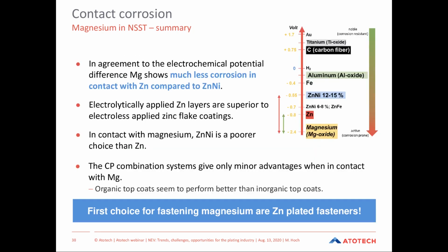To summarize the magnesium, in agreement with the electrochemical potential difference, magnesium shows much less corrosion in contact with zinc compared to zinc nickel, again highlighted by these two arrows here. The potential difference between magnesium and zinc is much lower.